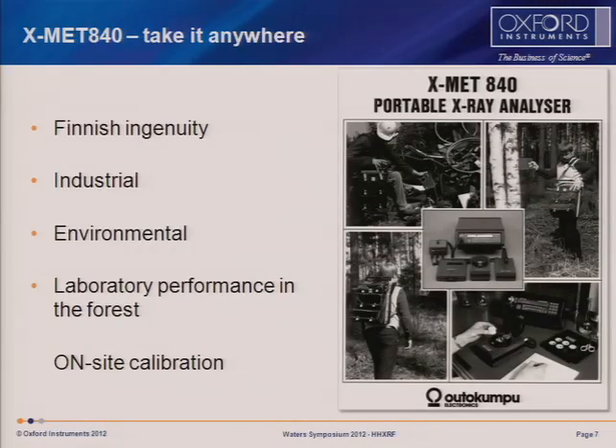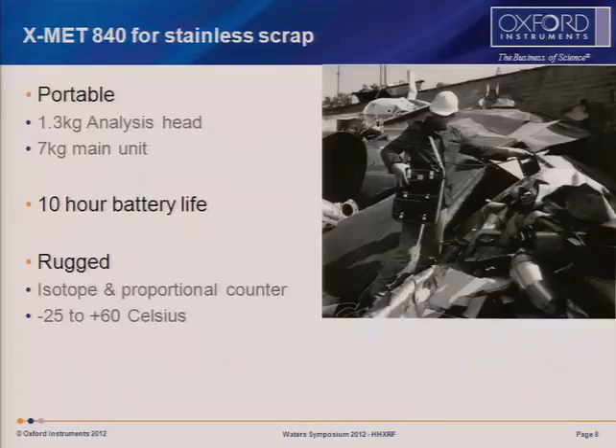However, Finnish ingenuity said, well, you can take this around. It's not portable in the same sense that Lee has just described, but that doesn't stop the Finns. They're quite happy to take it into the forest in a backpack and actually could demonstrate laboratory performance for some applications out in the forest, and could even calibrate on site with this equipment at the time. It was fine in stainless steel scrap as well. Here you see the handheld probe, the handheld unit, which has got the isotope in it.